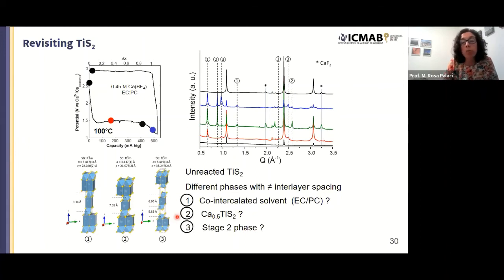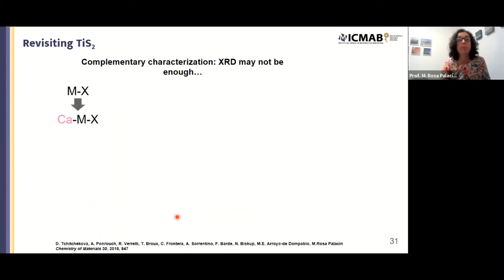And about the third phase, we are still not sure. It could be a stage 2 phase. But in any case, this is reversible, despite it's not really practical at the moment. So in this case, we had three phases. We were not able to refine the calcium occupation. So we really wanted to make sure that calcium went inside the crystal structure.